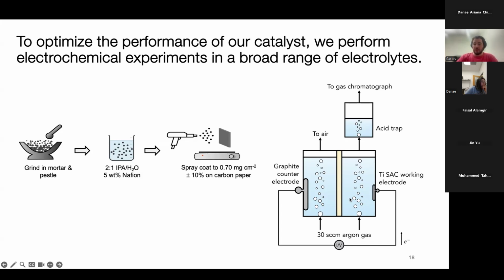And we put it in this H cell in which we have an electrolyte compartment on the cathode and on the anode, and then we sparge both sides with argon gas, and whatever comes out of this chamber goes into an acid trap and then goes into our gas chromatograph. So from the electrolyte chamber, we're able to quantify nitrates, nitrites, hydroxylamine, and we also quantified ammonia. In the acid trap, we quantified whatever ammonia volatilizes, and then in the gas chromatograph, we quantify hydrogen and nitrogen if we make any, which we don't make any nitrogen.